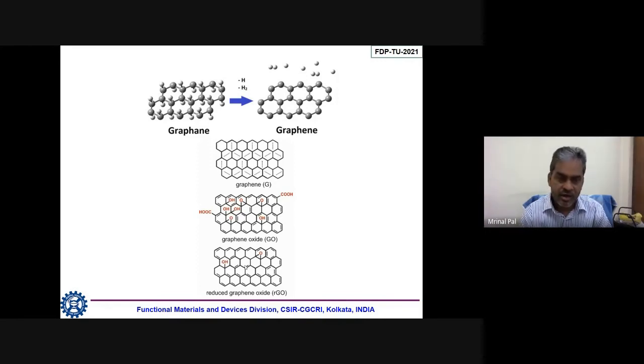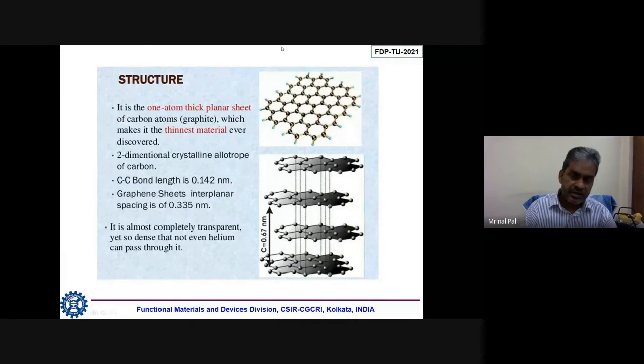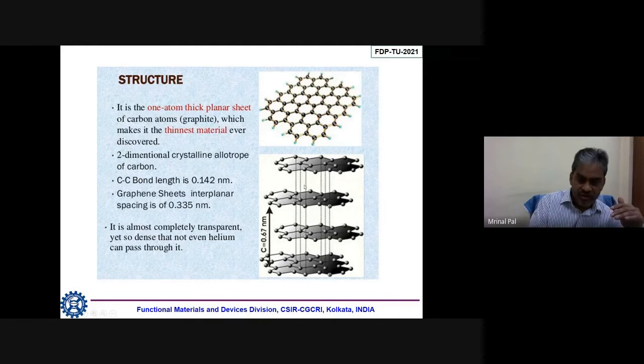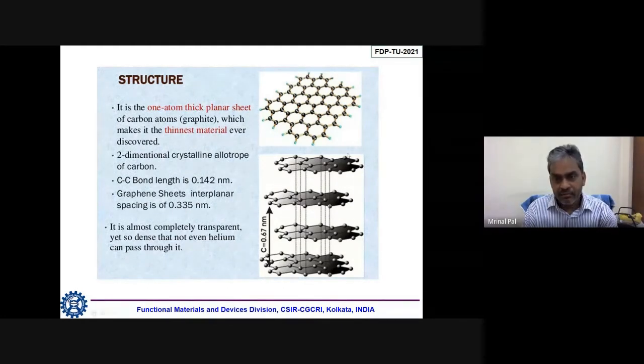Hope I am clear, and if you have any doubt, I can discuss this issue again during the question and answer session. So this is the graphene structure as I have discussed. This is nothing but sp2 bonding, and the distance between carbon-carbon bonds is around 0.142 nanometer. If we go to the graphite structure, the difference between the interlayers will be around 0.335 nanometer. But the beauty, why graphene is possible to prepare very easily, is because this interlayer bonding is a van der Waals bond, and that is very, very weak. So it is easily possible to break this van der Waals bond from the graphite and make single layer or few layer graphene.